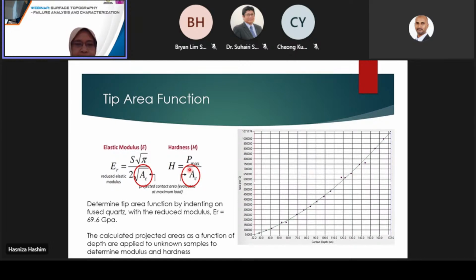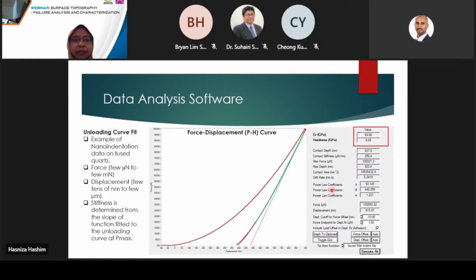So what we do here is a series of indents at various contact depths, with varying normal loads performed on fused quartz, and then the contact area and contact depth are calculated. By calculating the projected area as a function of contact depth on a known sample, we can then apply it to unknown samples to determine the modulus and hardness.